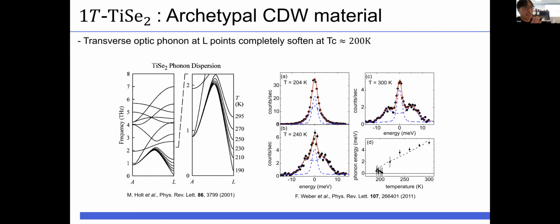So the displacement can be detected by measuring the phonon. It is known that the L phonons start to soften near the critical temperature and freeze at 200 Kelvin, which means that the energy goes to zero. The left figure is the calculated phonon dispersion, obtained by adjusting one spring constant, done by Holt and collaborators. From this dispersion, they could explain the thermal diffuse scattering pattern.